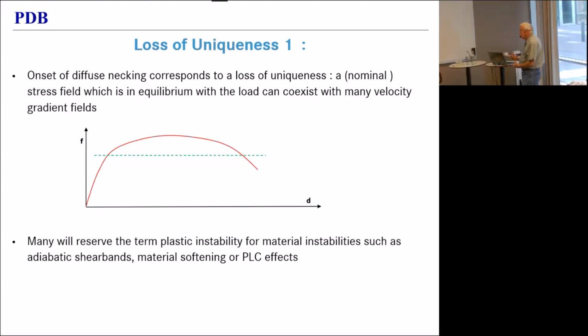Now, the term instability will often be reserved for material instabilities, and that could be adiabatic shear bands, it could be PLC effects, it could be material softening, it could be many things. I don't distinguish. Loss of uniqueness is bad enough. The point is, you become mesh dependent. So it's very important to know when it starts.